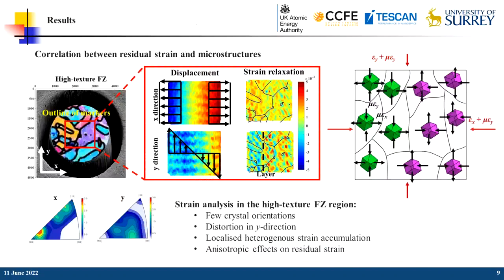So combined with the EBSD orientation map, we could correlate the microstructure and the residual strain at the final step of the time-resolved measurements. The overlaid EBSD map enabled the visualization of the crystallographic orientation, and this red outline reveals the position for the digital image correlation markers. The displacement maps in the middle disclose the corresponding deformation of the markers because of the residual stress relief. The residual strain can be further derived from the displacement map.